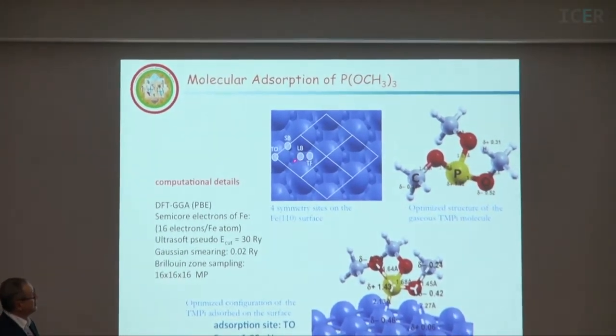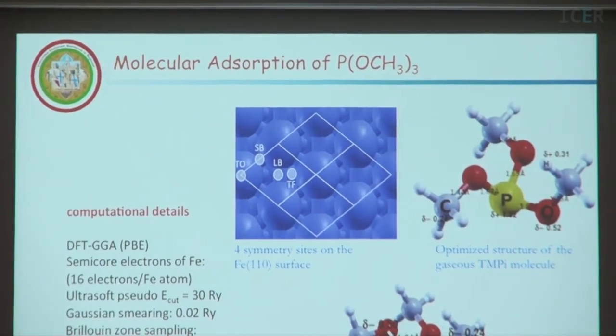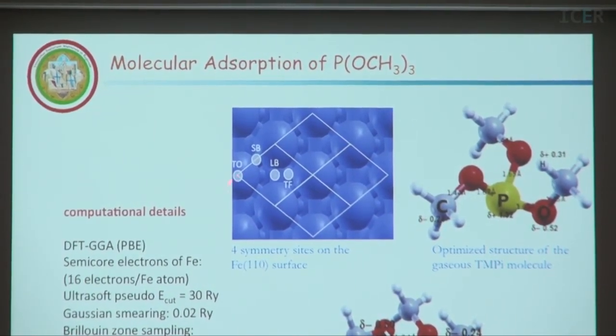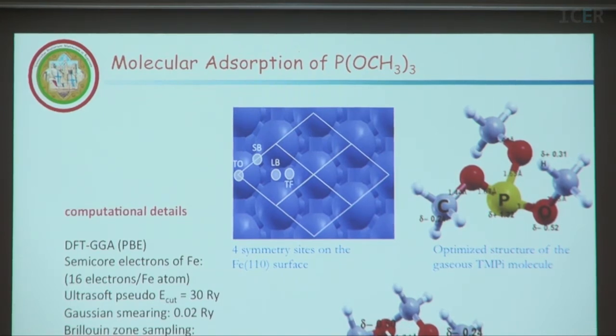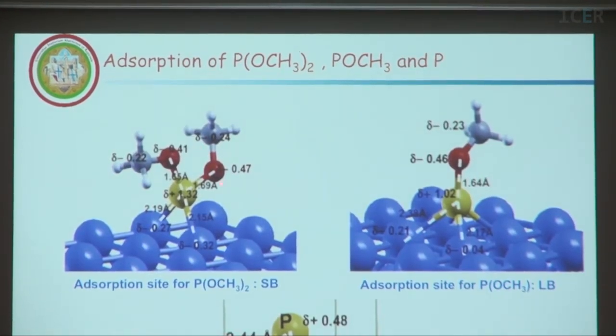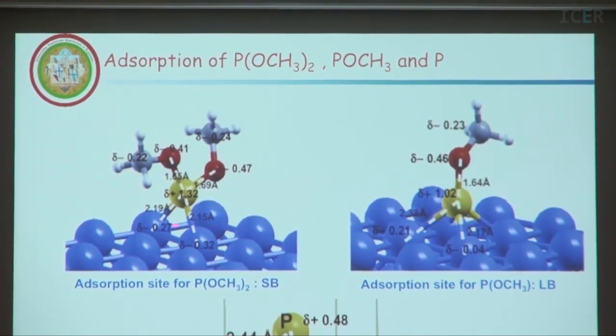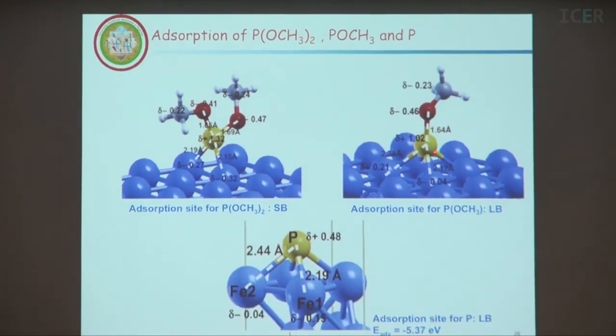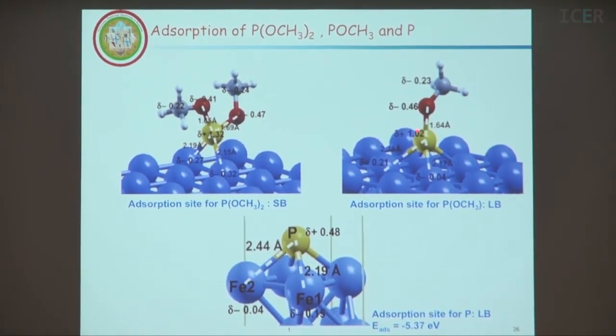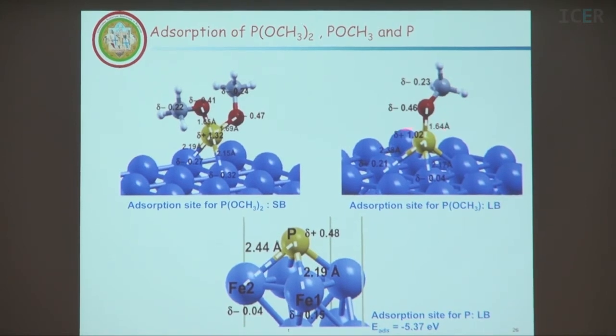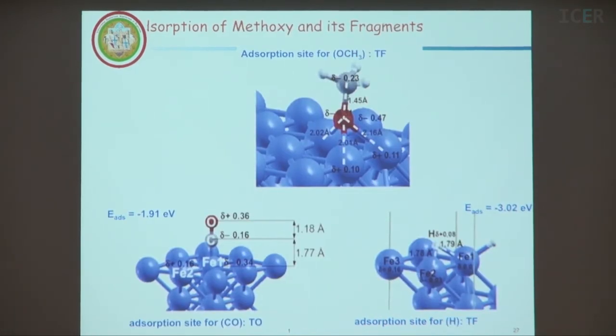If the molecule adsorbs to the surface, it adsorbs here by the phosphorus, and it adsorbs on this site. But after it is adsorbed on this site, the molecule is cut here. You can see the next. There are only two terminations. And now there is another site on the iron surface with 2 iron atoms. And it continues like that, cut again here. And now this is another site on the iron surface. And finally, it is cut here, and you get the phosphide, the iron phosphide that we analyzed in our experiment. So by computer simulation, we can see exactly the pathway of the reaction.